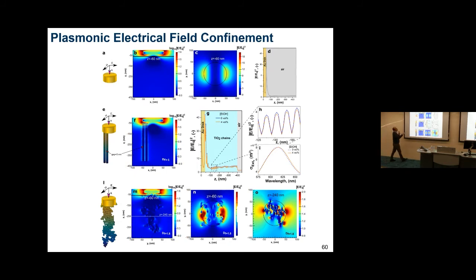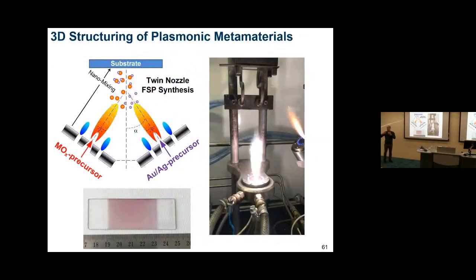Then we model what happens if we have a chain, a fractal with a dimension of 1, of nanoparticles. Interesting enough, there is still some electric field going on after a very high distance. And what happens if we have our fractal structures, done with the particle simulation I showed before, is we see hotspots distributed much above 300 nanometers. This was very interesting to observe and explains why our larger volume, concentrating the gas molecule where there is the electric field, can enhance the response.